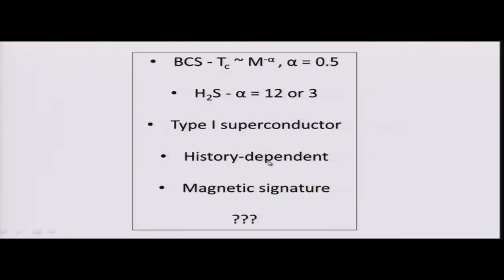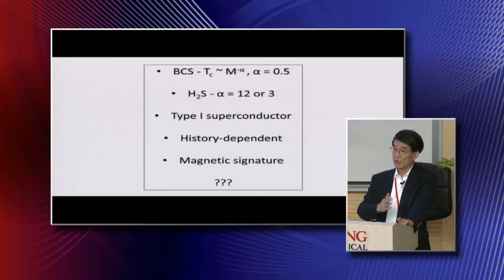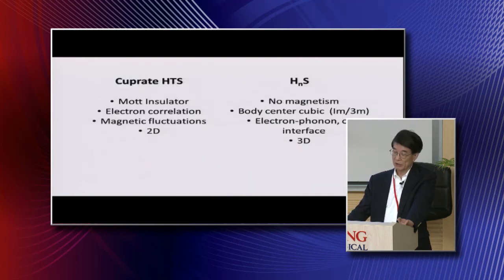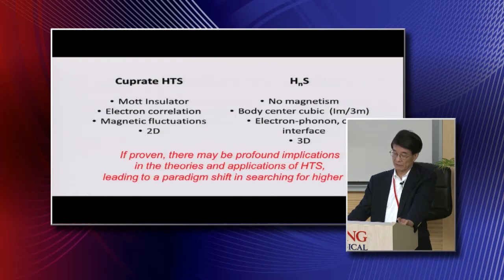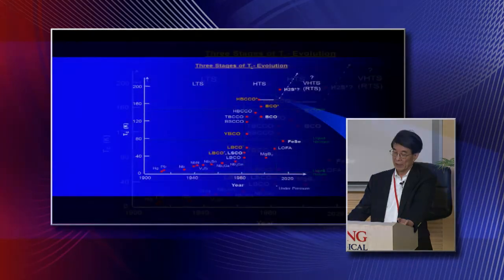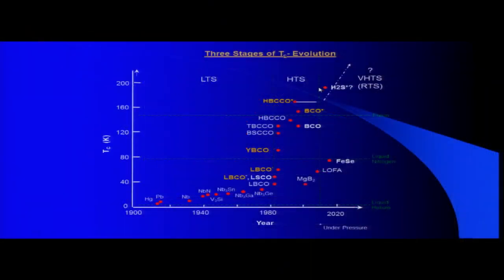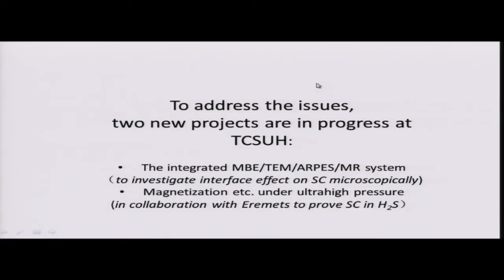And there's also history dependence. It's not that you apply pressure and it becomes superconducting. You have to cycle it a little bit, and what's the reason? And there's no magnetic signature measured at this moment. So what's the reason? Now, the implication of this, if it is true, is that it will change lots of things. I'll come back to this slide if I have time. And so the Tc now is up to this point, where we continue to go up. Based on the trend, it looks like it may go up, but we have to change everything.